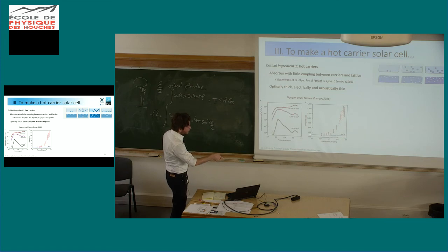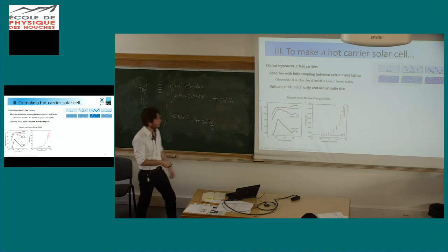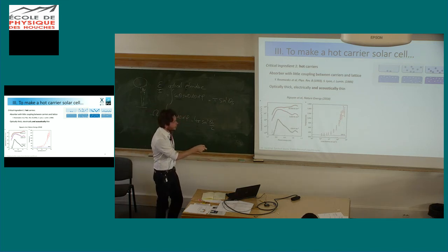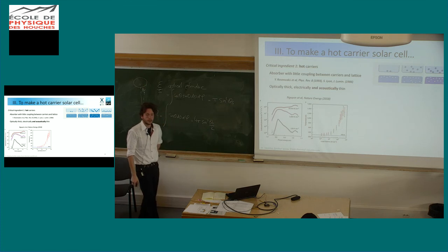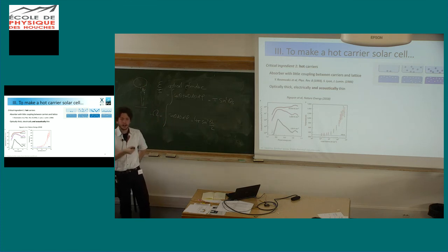As you increase laser power here, for instance, you see that the carriers' temperature, which is extracted from the luminescence techniques Laurent has presented before, goes up and up and up. So you can generate hot carriers indeed. We know how to generate hot carriers. We know how to do this.